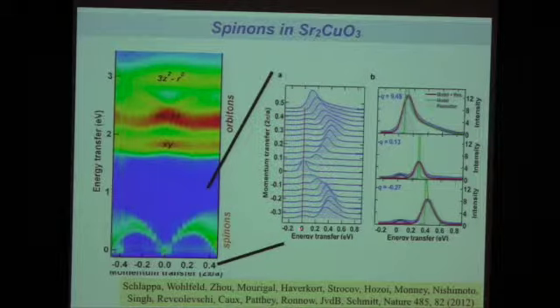So this is the data. This is energy transfer, so lost energy, for different momenta. You see there is a nice set of dispersing excitations, but they are always broad. There are tails here. Those tails are the textbook signature of spinons, of continuum excitations. Here, for three momenta, I've shown the data and the calculation, which is the Bethe ansatz solution of the Heisenberg model, giving you the green line. If you take the Bethe ansatz solution and convolute it with the resolution, you get this red line, which basically is on top of the data.